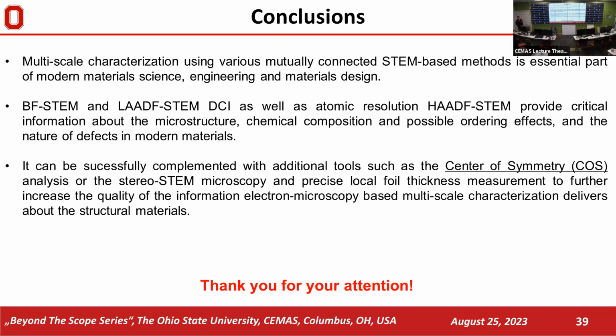Now about COS, that's a more tricky question, definitely, and I think we have to be careful, especially if you're dealing with a specific defect. When we tried the Nye tensor study, which is more sensitive to the placement of atomic columns, not every experiment worked. Sometimes with COS we knew the dislocation was there, COS was showing that the defect is there, but the Nye tensor was not showing it because of channeling or thickness-associated effects. So it's definitely something worth trying to pursue.